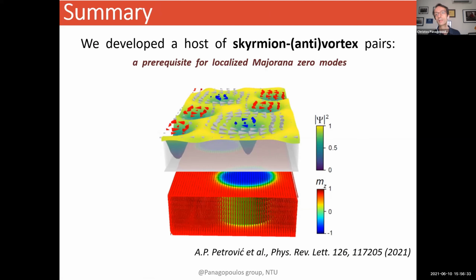Right. So in fact, the main limiting parameter is not, I wouldn't say temperature, but the superconducting parameters. In other words, you need to match the superconducting coherence length and the superconducting magnetic penetration depth to the size of your skyrmion. Having, indeed, as you correctly said, the superconductor used here has a low transition temperature. It's only a few degrees Kelvin.